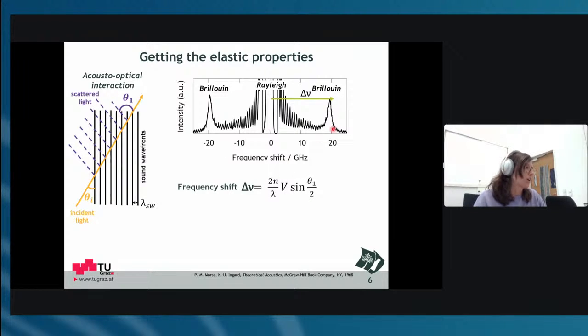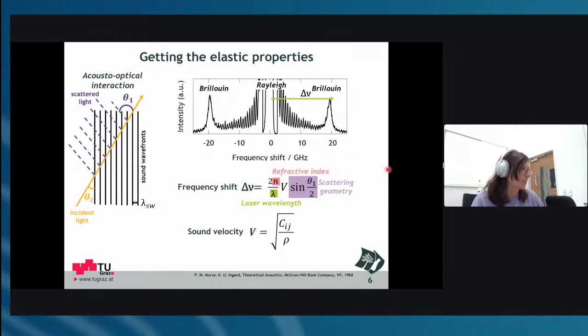From the frequency shift, you can determine via this formula the sound velocity in the material. And this is related via the refractive index of your material, the laser wavelength that you are using, and the scattering geometry, as I was mentioning. So the way you shine into the material and how you collect the scattered light from your material. You will see later that there are different scattering geometries that can be applied, and that changes this formula a little bit around. But basically, this is the first main formula, and here already comes the second, which is